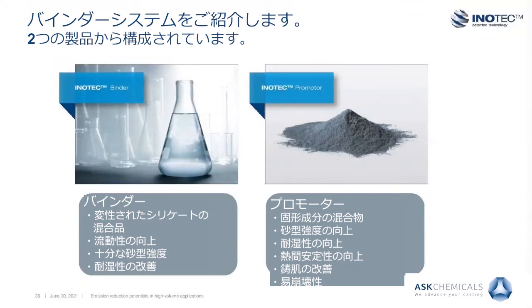The INOTEC technology is described as a two-component binder system. Component 1 forms the liquid INOTEC binder, which can be described as a modified solution of alkali silicates. The binder has a strong influence on specific properties of the molding mixture, for example, flowability, and the core itself. Characteristic strength profiles with adjustable humidity resistance properties result in dependency of the type of product used.